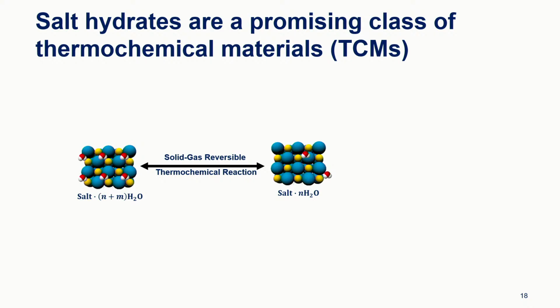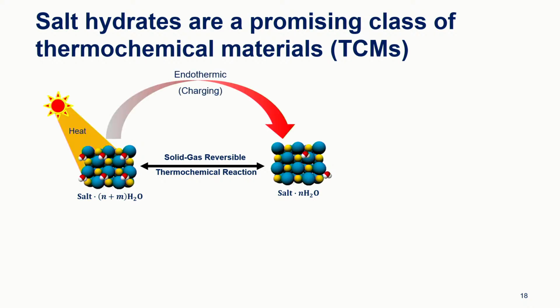So how does it work? We have our salt hydrate, and if we apply heat, we start dehydrating the material. That is an endothermic reaction, supplying energy, and we're charging our thermal battery in that process, and we release water molecules. So you get a dehydrated version of the salt.